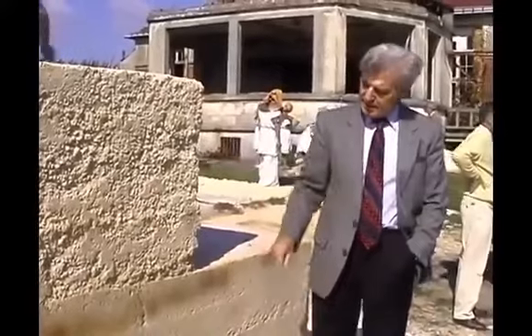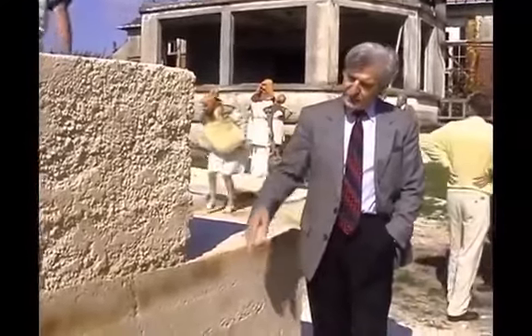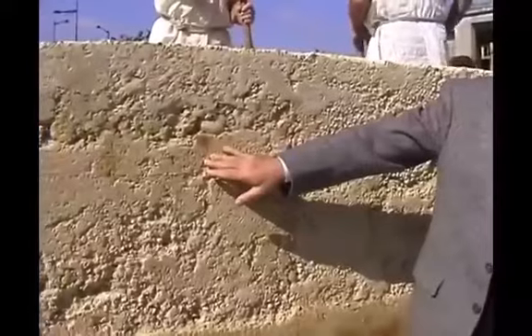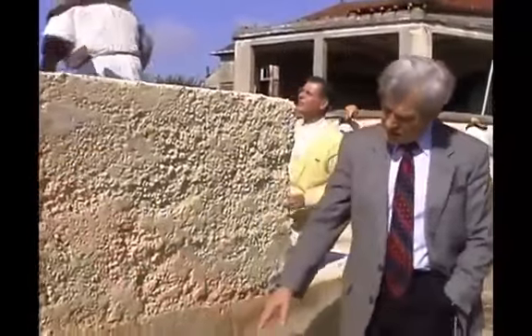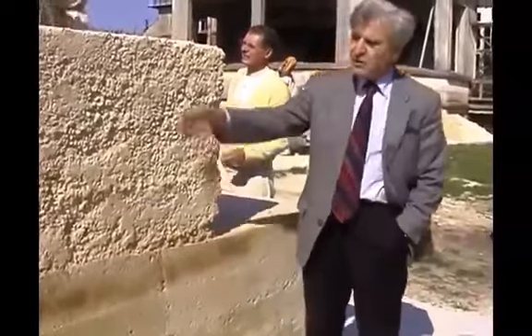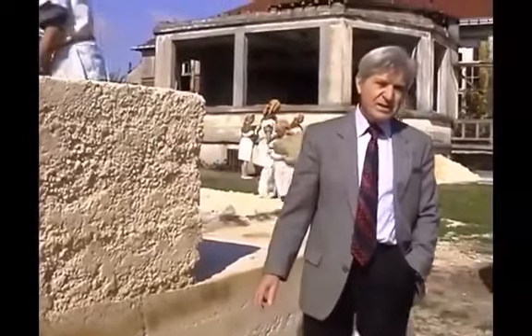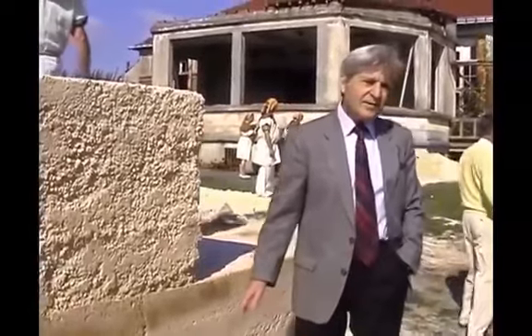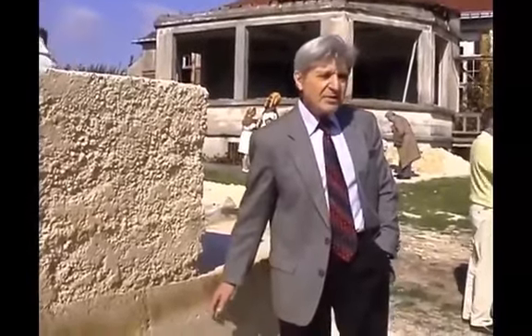4 blocks have already been made. Joseph Davidovits presents them. The 2 large blocks weighing up to 4.5 tons, containing most water, have given smoother surfaces. The 2 small blocks weighing up to 1.3 tons, the least wet, take on rougher surfaces. When you look at the stones of the pyramid, this is what you see. You see either smooth blocks or very crude blocks. And we have replicated all these surfaces just by varying the amount of water, which depends on the climate, which depends on the weather. Joints between blocks are also perfect.